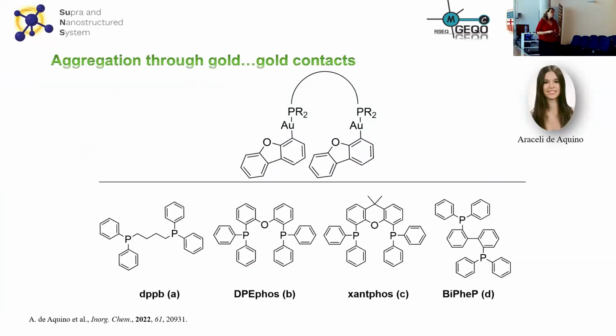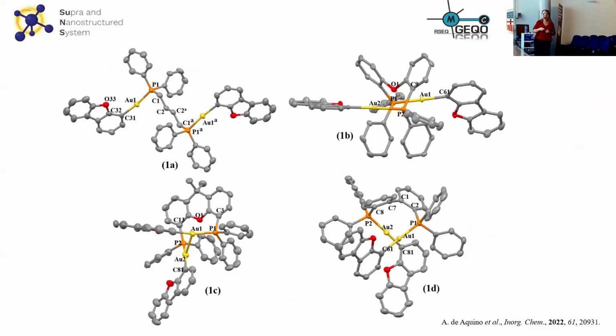Okay, so what about the photophysics of aurophilic interactions? I explained what happened in solid state. Can we translate the same results to solution? Well, we have some differences in what we observe in solution. In this case, more recently, we also performed a systematic study with different diphosphine dinuclear compounds with a chromophore. These dinuclear compounds are connected by a diphosphine that also differs in flexibility, as we can observe here in these four cases. In all cases we could also grow single crystals suitable for X-ray diffraction,